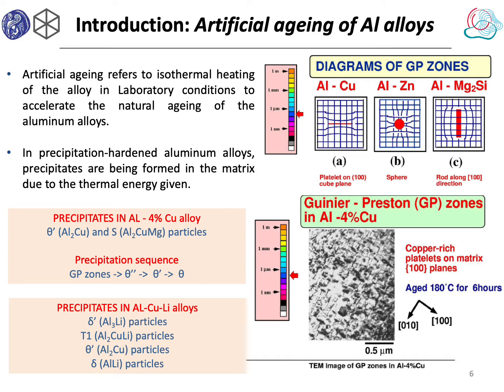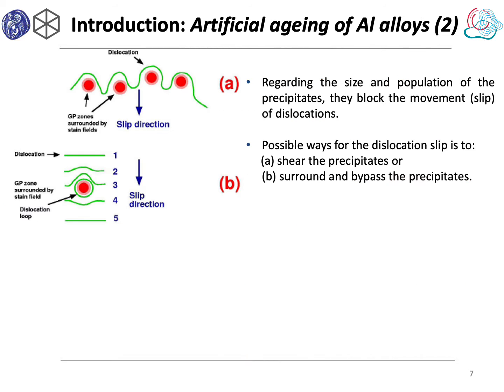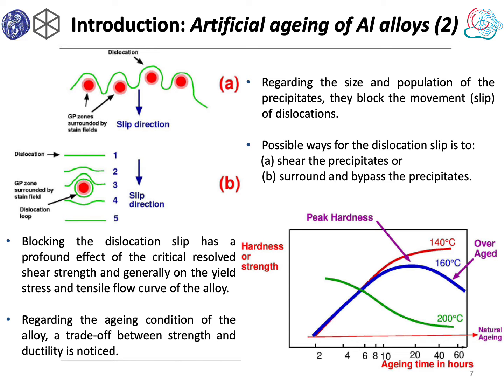This alloy is a precipitate alloy. By this I mean that with natural aging or with artificial aging, the quasi-static properties are changing. We don't have one mechanism, but we have 4 different, so that makes the situation more difficult. But why do we need these precipitates? Because they are blocking the dislocations. By blocking the dislocations, you can increase strength and you sacrifice ductility.